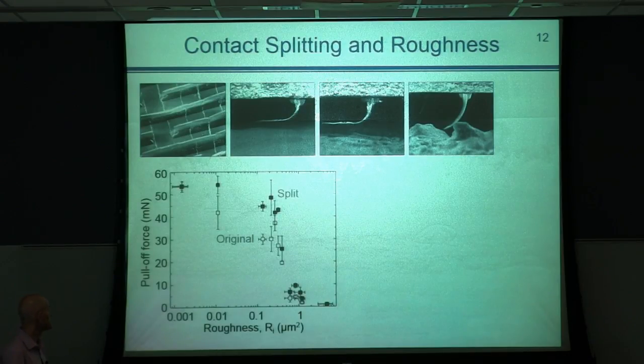So we can indeed see that when we have a smooth surface, then pull-off force is not affected by contact splitting. So long walls operate the same way as the walls cut in shorter sections. But when the roughness starts increasing, we can clearly see that pull-off force drops quite fast. And when we have structures that are split into shorter sections, then this split surface is able to withstand detrimental effects associated with roughness in a much more efficient way.